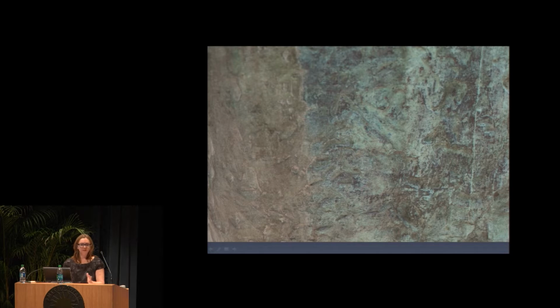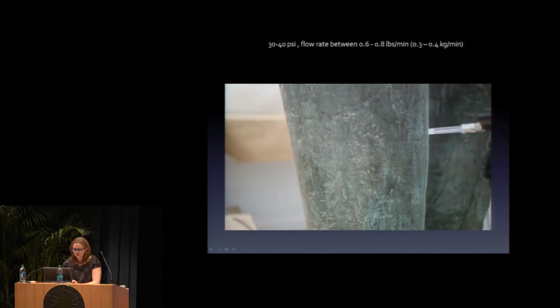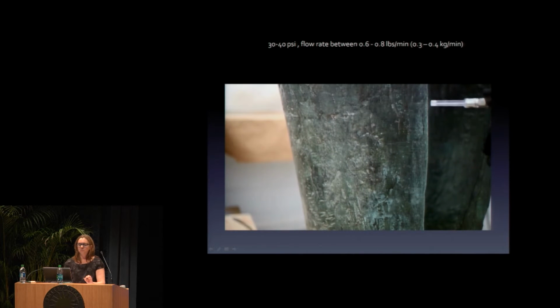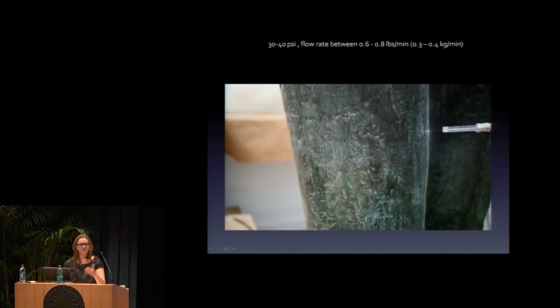So we started off by testing using the carbon dioxide blasting just to remove the wax. Well, that was what we expected we would get. And in order to preserve the chemical patination, probably a cupric nitrate, which was pretty well bound, we didn't want to use too much pressure, and we really wanted to preserve that. So we just did the carbon dioxide blasting, we have a video, I'll start that, just to remove the wax layer. And then we did a little bit more analysis, and we were able to see that there was Incralac still underneath. Then we used a solvent acetone cleaning to remove the Incralac.